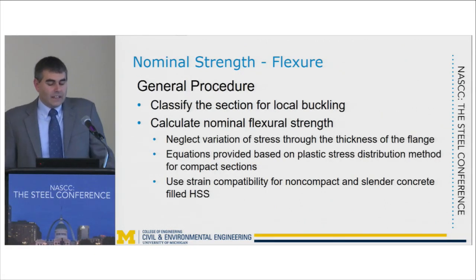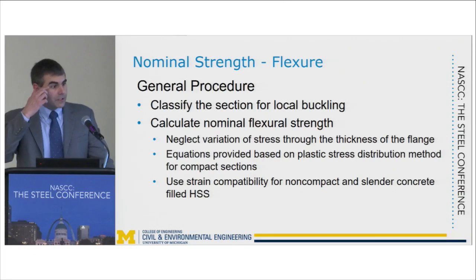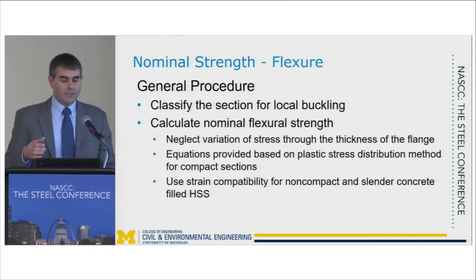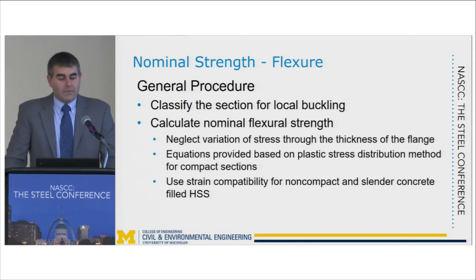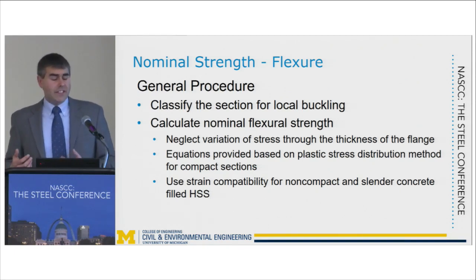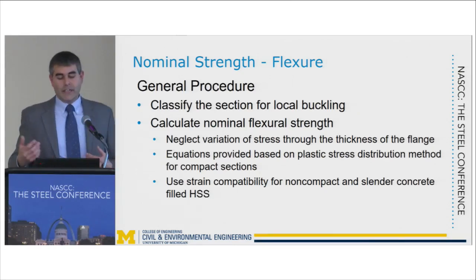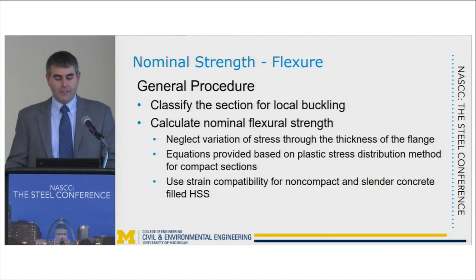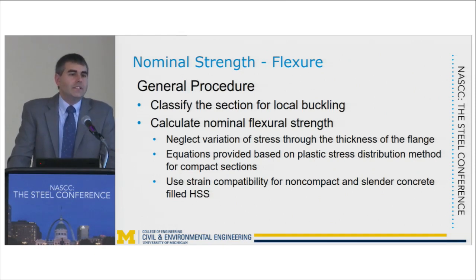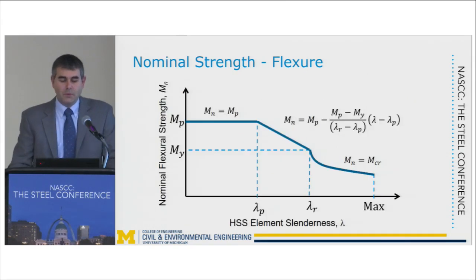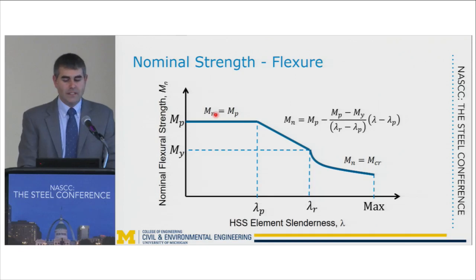Now, the general procedure is to again classify the section for local buckling and then calculate the nominal flexural strength. When you're calculating the nominal flexural strength, you're typically going to neglect variations of stress through the thickness of the flange. You're going to use equations based on a plastic stress distribution method if you're dealing with a compact section, or you're going to use the strain compatibility method for a non-compact or slender section. Now, I will say there's less information in Chapter I in terms of dealing with flexural capacity and calculating the nominal strength because it's a little more complex. But what it ends up coming down to is, if you plot the nominal flexural strength versus the element slenderness ratio, for a compact section, it's pretty straightforward, it's Mp.